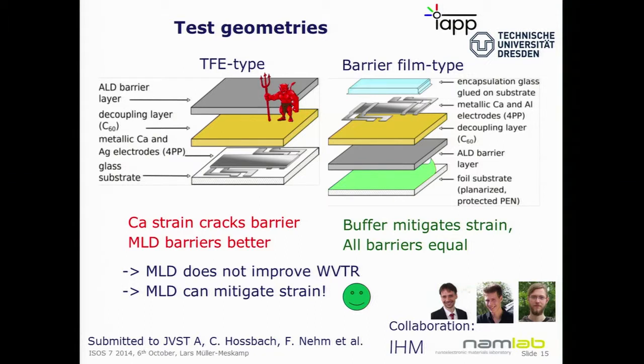If you do it in the barrier film type measurement, so we have the polymer at the bottom, then the ALD barrier, then decoupling layer, calcium, and our back encapsulation, it looks like all barriers are equal. So the C60 layer can mitigate the strain, no problem. So the MLD does not improve the WVTR, but apparently it can mitigate the strain and increase the durability or the flexibility of the barrier, even if this is an indirect proof.